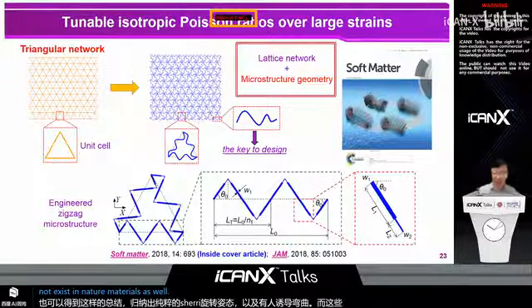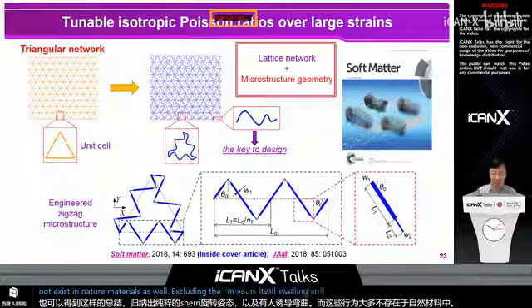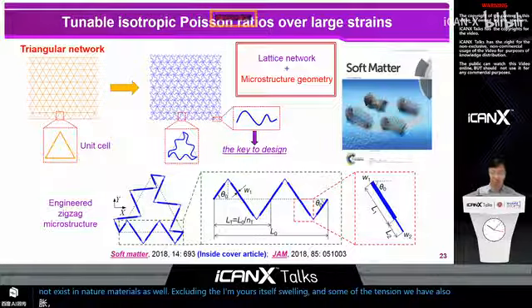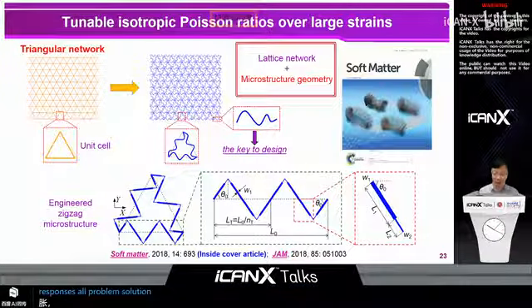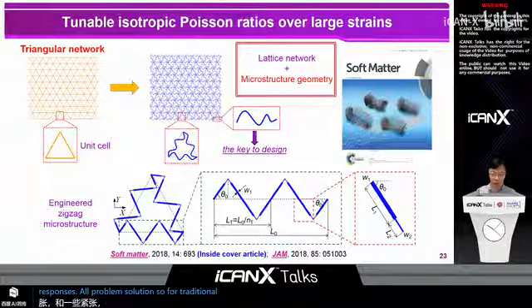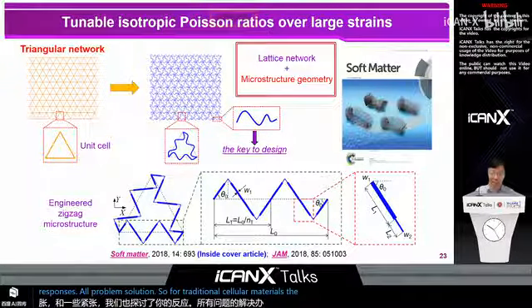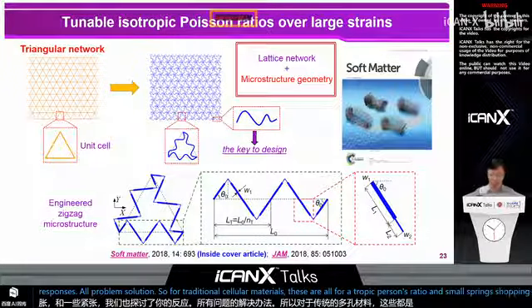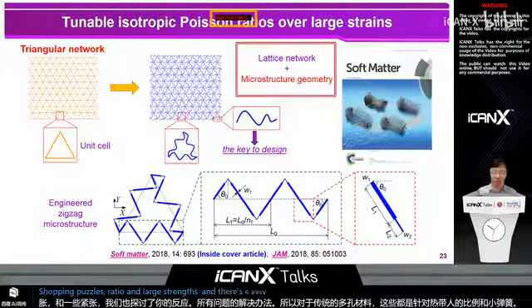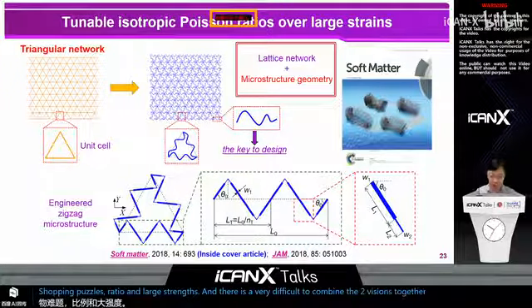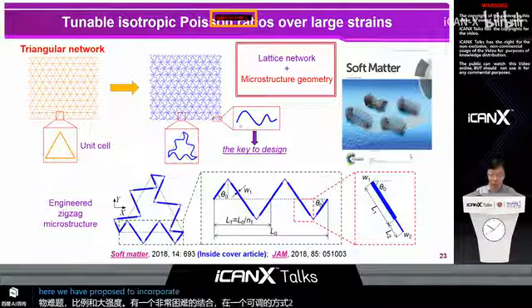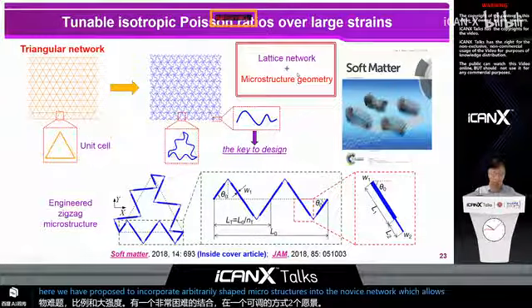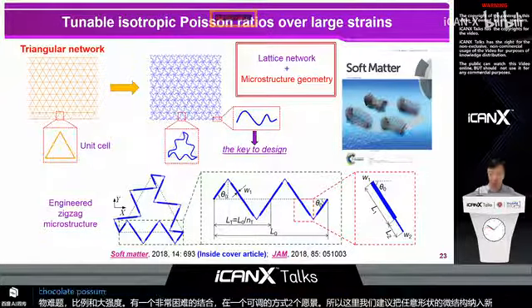Excluding the unusual responses of swelling and thermal expansion, we have also explored the unusual responses of Poisson's ratio. So for traditional cellular materials, they either offer isotropic Poisson's ratio at small strains or anisotropic Poisson's ratio at large strains. And it's very difficult to combine the two features together in a tunable manner. So here we have proposed to incorporate arbitrarily shaped microstructures into the lattice network, which allows us to achieve tunable isotropic Poisson's ratios at large strains.